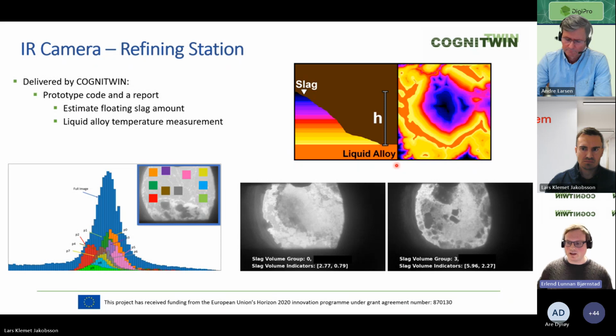So here we say that the colder the slag is, the thicker it is. So we're assuming that you have this heat falloff. And then here you can also see that the thinner the slag is, the warmer it seems to be. This is due to the difference in emissivity between the two phases. So this makes it sometimes difficult to tell the difference between the slag and the alloy, which is one of the issues that we had to deal with.